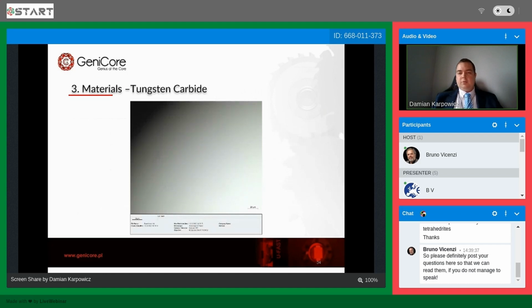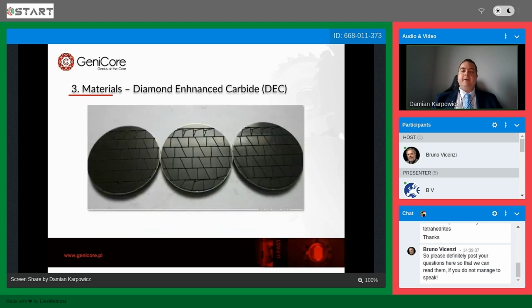And as you can see, the mean value of HV10 was 2,515, which is quite a good result in their opinion. And no porosity at all. So as we can see, the good sides of SPS technology are visible here. For diamond enhanced cemented carbide, so the material produced with the pulse plasma compaction technology, it was quite hard for us to start selling this material because besides selling the devices, we are also producing DEC material, as probably mentioned before.